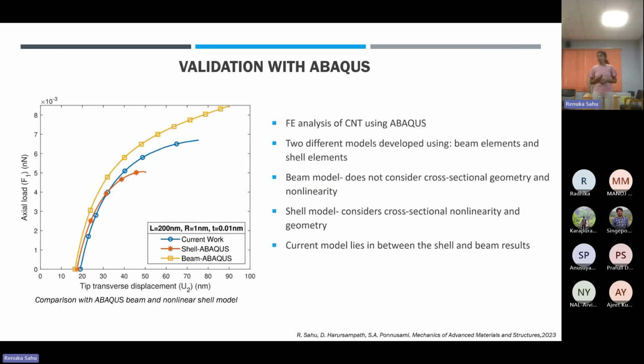We further validated the result with an Abaqus finite element model. For this case, we used two different models: beam elements and shell elements. The beam elements in Abaqus do not consider the cross-sectional geometry or the non-linearity, which is why the beam model gives a much higher buckling load compared to the shell model, which considers the cross-section non-linearity and geometry. Our current model lies somewhere in between the shell and beam results.